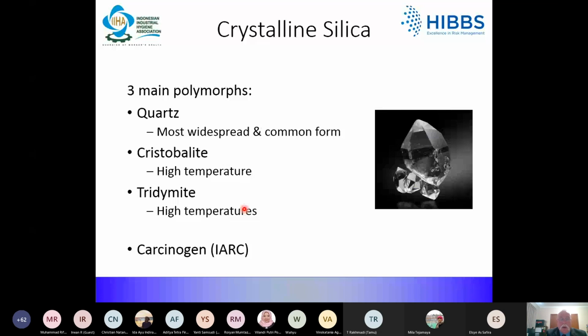In construction, the most common form of crystalline silica is quartz, and it's most unlikely that you will encounter either cristobalite or tridymite. Now, cristobalite can be found where amorphous forms of silica have been calcined at high temperatures, generally exceeding 1,000 degrees C, and the silica is then converted into cristobalite. And cristobalite is also present in engineered stone. So that's the type of stone that I was talking about previously. Tridymite can also be formed at very high temperatures, but usually at low pressures and as a byproduct of some chemical processes. I doubt that you will ever encounter it